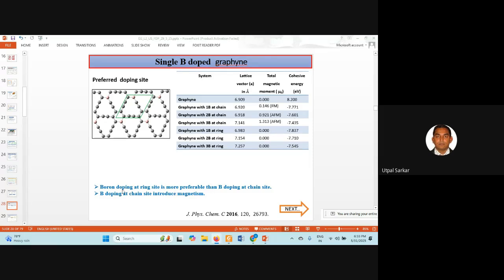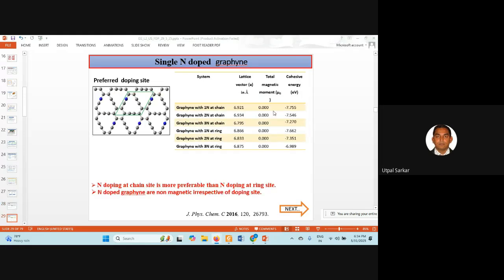So boron doping at ring site is more preferable than at chain site, if you see the cohesive energies, and boron doping at chain site introduces magnetism. However, for nitrogen doping, you see there is no magnetism here, so these nitrogen dopings are basically non-magnetic in character, and nitrogen doping at chain site is more preferable than nitrogen doping at the ring site. You see here this is larger than this. Okay, corresponding one. So this one and this one, this one and this one, and this one with this one.